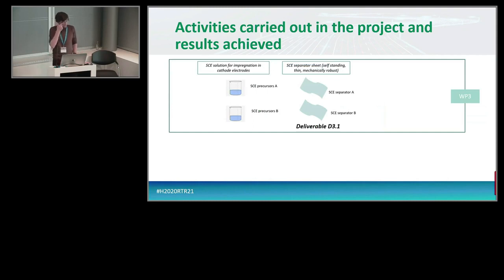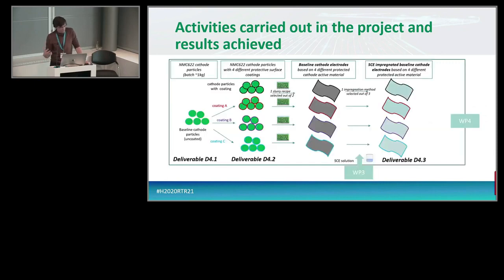So a few schematics on what we have done. It's only schematics that I'm showing here. For the SCE, the solid electrolytes, we want to impregnate it into the cathode to really surround all the active material and have a good contact there with the cathode material. We also want to have it as a sheet, to have a separator sheet between cathode and the lithium metal anode. So here we are comparing different recipes for the precursor solution, starting from the first recipes available at IMEC at the beginning of the project, together with the partners, mainly Solvionic in this case, using their know-how on solid electrolytes as well, and on polymers as well. We defined different recipes. We made different separator sheets, and we selected one of these to be put now into the cell. So one of these has been selected and is going to the cell level at this moment. Similar approach for the cathode.